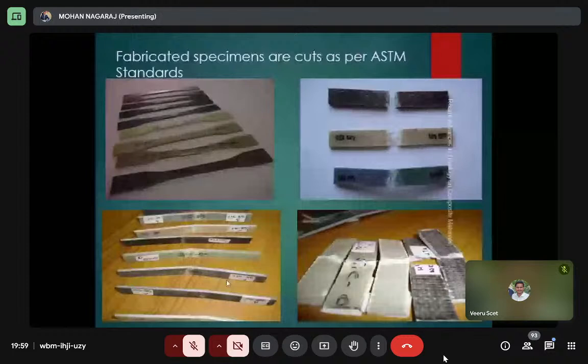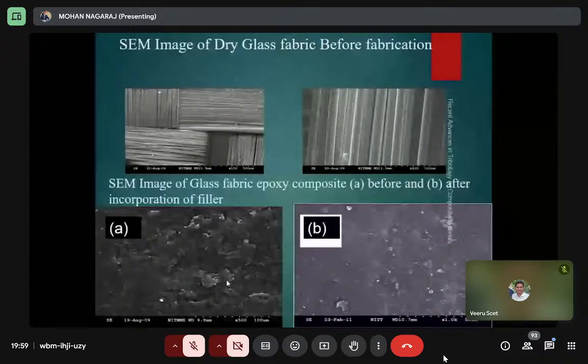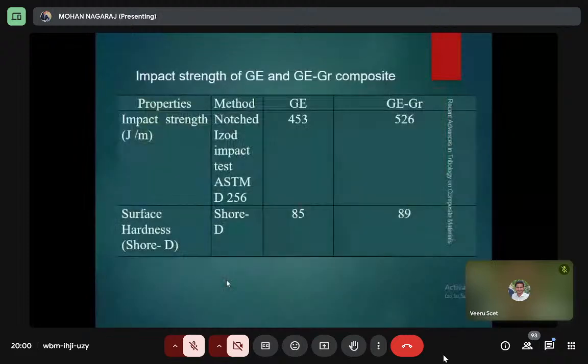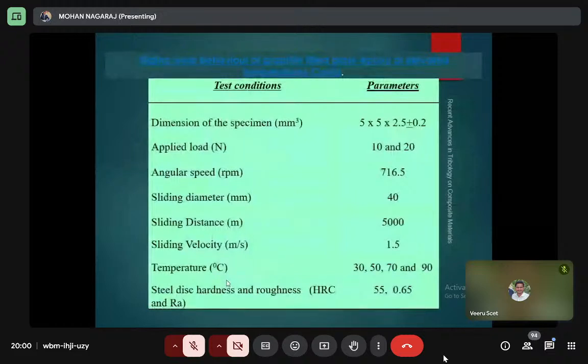ASTM standards. So there are tensile, impact and also wear tests going on. This is the SEM images of before fabrication and after fabrication, after incorporation of the fillers in the materials. This is the impact strength studied for filler filled composites. With graphite, it gives more impact strength and more hardness as compared to the normal glass epoxy